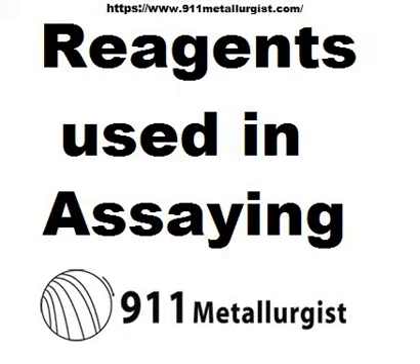Iodine is soluble in alcohol. Nitric acid, HNO3, specific gravity 1.42, boiling point 121 degrees centigrade, contains 70% by weight of hydrogen nitrate. It is convenient to remember that 1 cc of this contains 1 gram of real acid. It combines the properties of an acid and of an oxidizing agent; 1 cc contains 0.76 gram of oxygen, most of which is very loosely held and easily given up to metals and other oxidizable substances. Consequently, it will dissolve many metals upon which hydrochloric acid has no action. All sulfides — that of mercury excepted — are attacked by it and for the most part rendered soluble. It has no action on gold or platinum, and very little on aluminium.